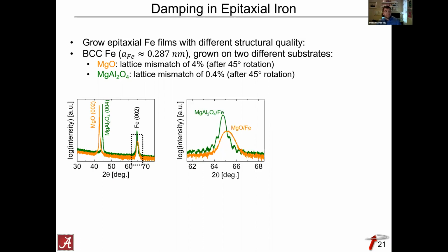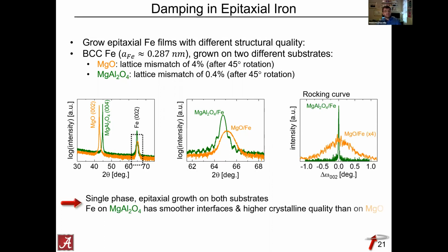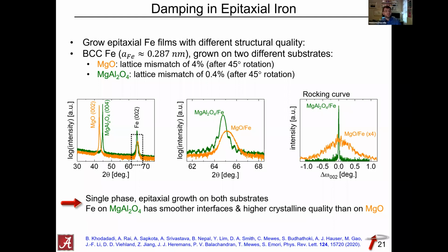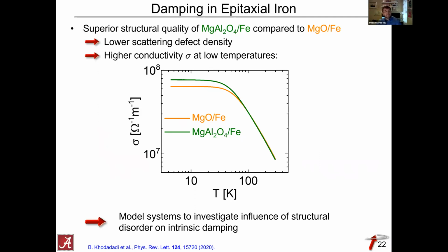The X-ray diffraction confirmed what we were hoping for. Here's a rocking curve for the crystal quality. Both films grow single phase and epitaxially on both substrates. However, the iron on magnesium aluminum oxide has a much smoother interface and a higher crystalline quality than on MgO. That's something to keep in mind as we move forward. The better structural quality of the films grown on magnesium aluminum oxide means a lower scattering defect density, so you get a higher conductivity at low temperatures, which you can see here as the green curve in this graph. This gives us a model system to investigate the influence of structural disorder on the intrinsic damping in these iron films.